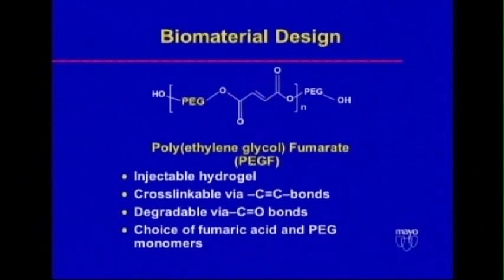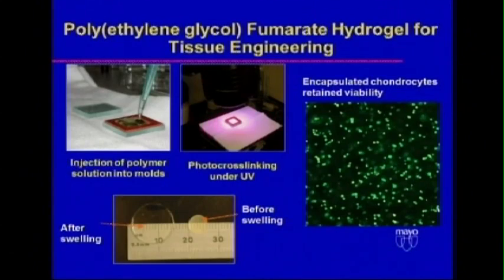Now, let's look at a different one. We thought, okay, we made polycaprolactone fumarate. What else can we use? PEG is something that we use a lot, and we wanted to see if we could put PEG together with fumaric acid with the idea of making something injectable, because PEG is very hydrophilic, and we wanted to see if hydrogels would be useful. So this is something that Seon Joo made when he was working in Tony Mikos' lab, and we worked together on trying to make an injectable hydrogel. We've since modified this PEG fumarate in a lot of ways. We currently use it in both our bone and nerve programs. This is Maryam Tabatabai's work.